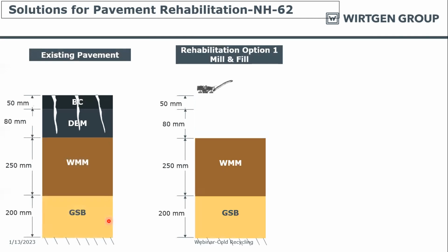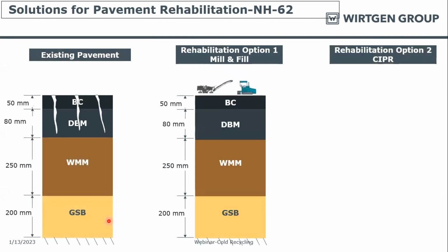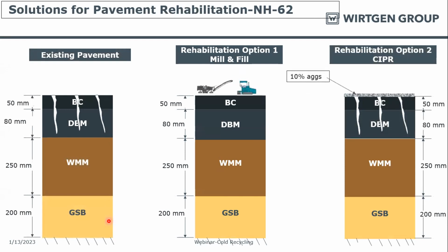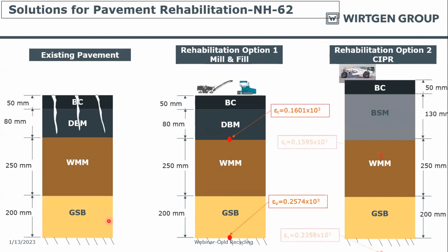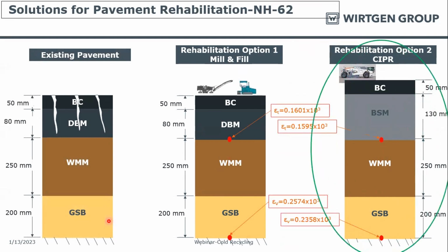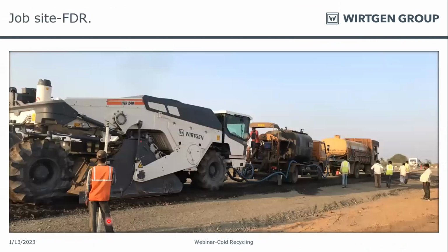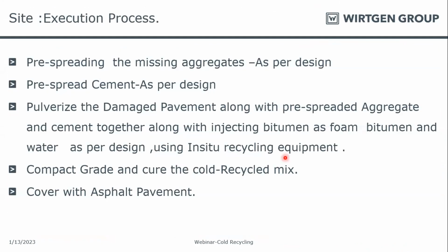There are two options. Here we recycled 130 mm in situ with addition of 10% fresh aggregates, and we then sealed it with 50 mm BC. These are some of the strain values for fatigue and rutting criteria. These are the job site pictures. Here you can see the bitumen tanker and a water tanker, which is coupled to the machine.